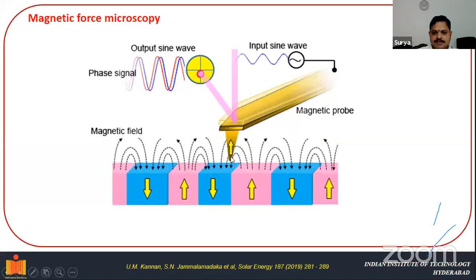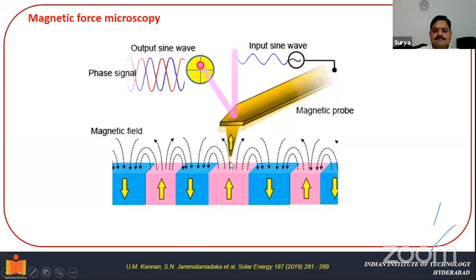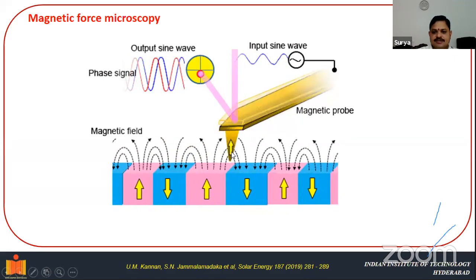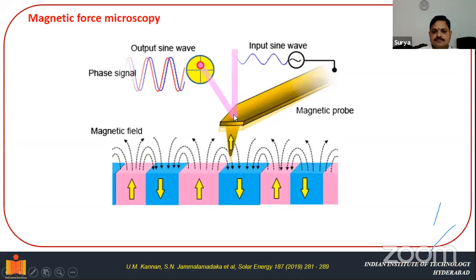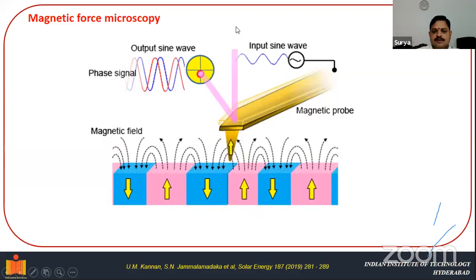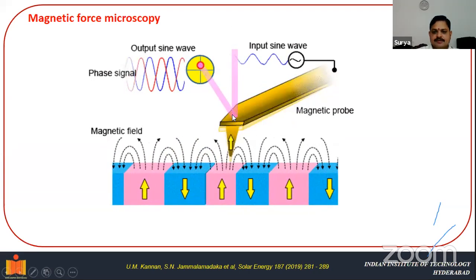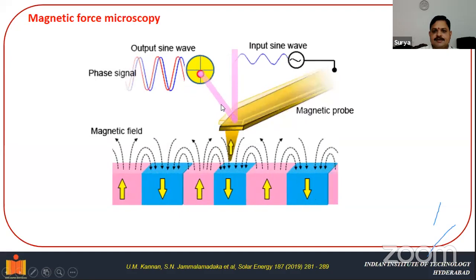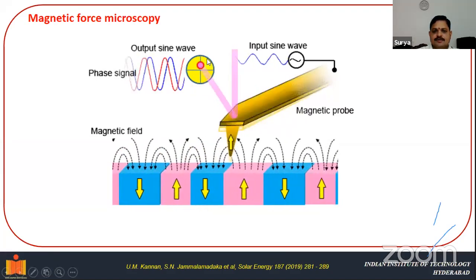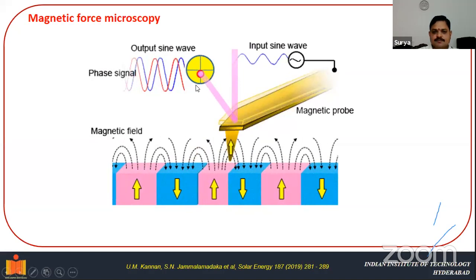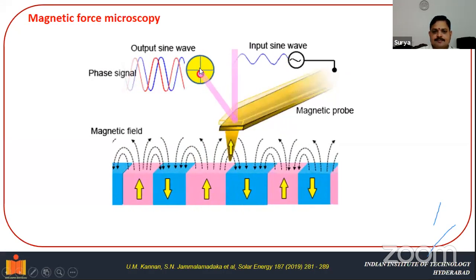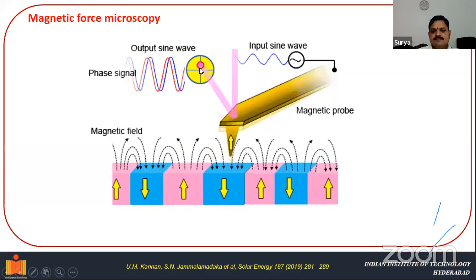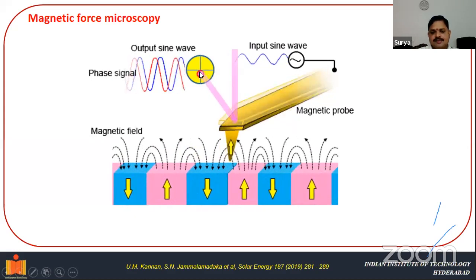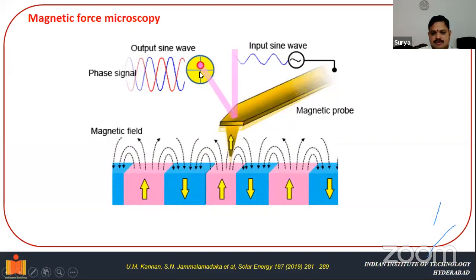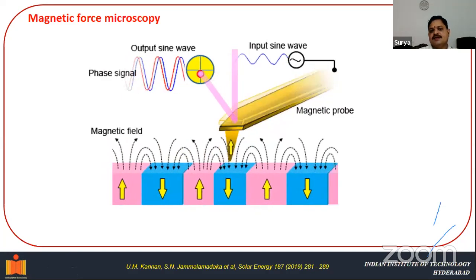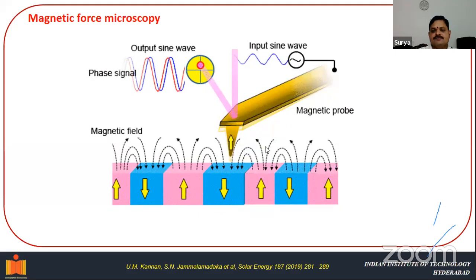In atomic force microscopy, there will be repulsion due to this fact. The tip will move back and forth. As we impinge laser light at the edge of the tip, there will be deflection of this laser spot. We use a photodetector, a position sensitive detector, which will detect the position of the laser spot. From the position of the laser spot, we can image the surface, whether it is smooth, rough, or discontinuous. Such information you can get from the atomic force microscope.